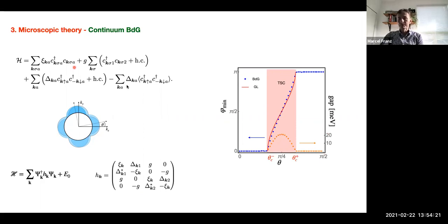So this maximum gap delta is about 45 meV, so the minimum gap is almost a half of that. So this is not small. This should be visible through basically any spectroscopy, such as tunneling or angle resolved photoemission. This should be visible in specific heat, for instance, because it's a sizable gap.